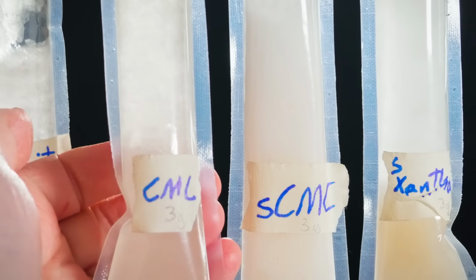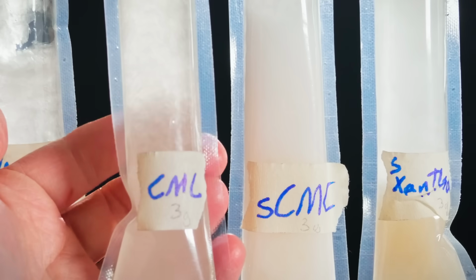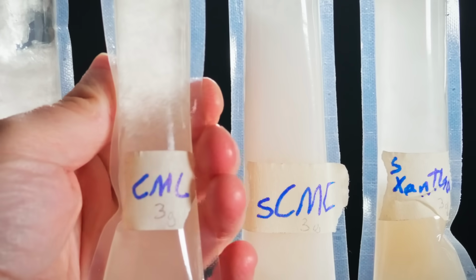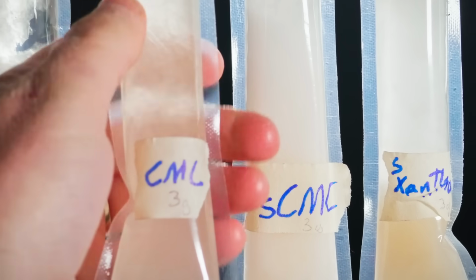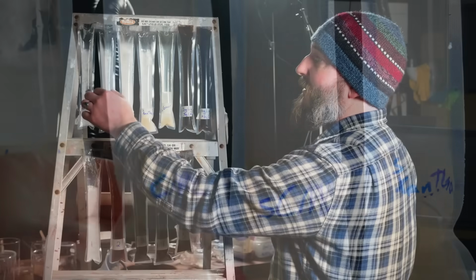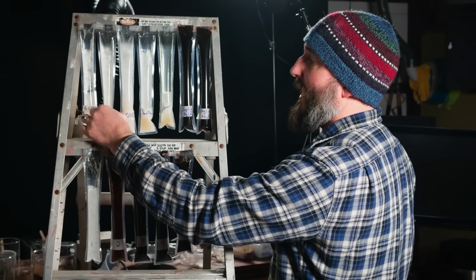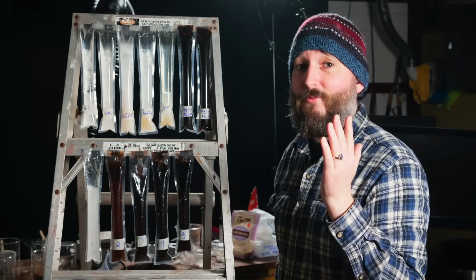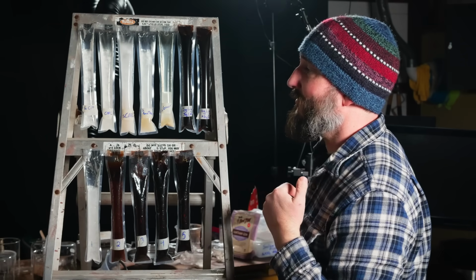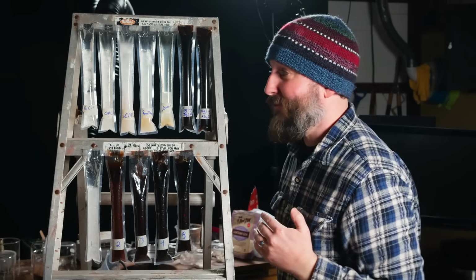And that might be an issue. The original CMC is well distributed, but the crystals are fairly large. Some good and bad there. CMC is known to stabilize PCMs, but it also reduces their thermal capacity. Hopefully that is reversed with the sulfonated compounds, and these should actually increase the thermal storage.